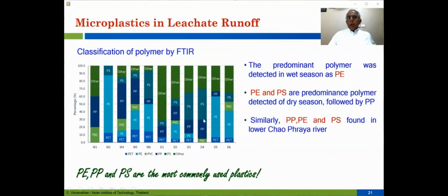In a similar way, we looked at different components in detail, the different sampling locations in the wet season and the dry season. You can see, it's very important. The predominant polymer seems to be, in all cases, polyethylene. Polyethylene and polystyrene are the predominant polymers detected in the dry season, followed by polypropylene. So it's a very interesting observation.